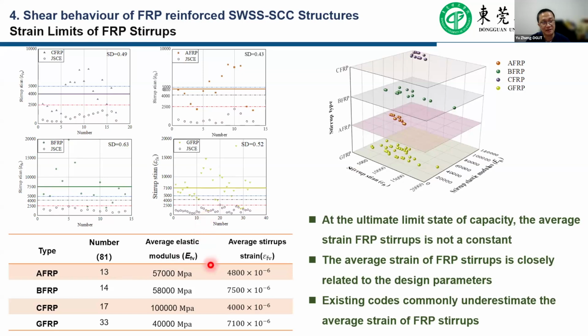In the beginning stage, we can find that with the changing of the FRP material for the FRP stirrup, at the ultimate state capacity, the average strain of the FRP stirrup is not a constant, and the average strain of the FRP stirrup is closely related to several design parameters. And the current design commonly underestimates the average strain of the FRP stirrups. Those will be changed by the FRP materials.